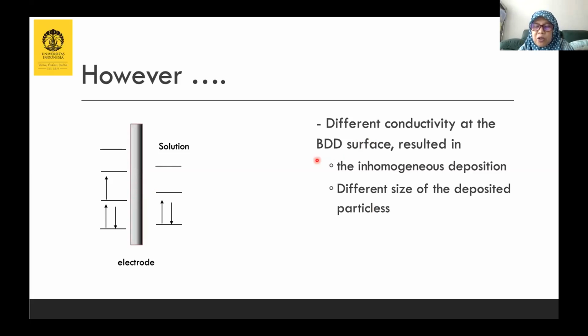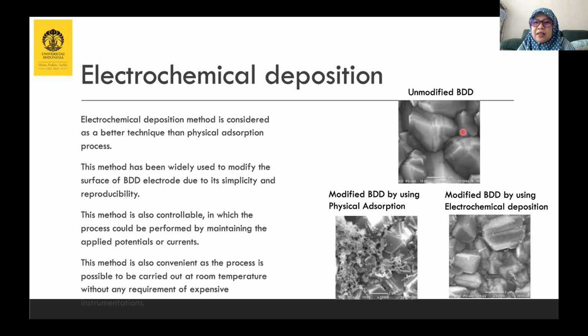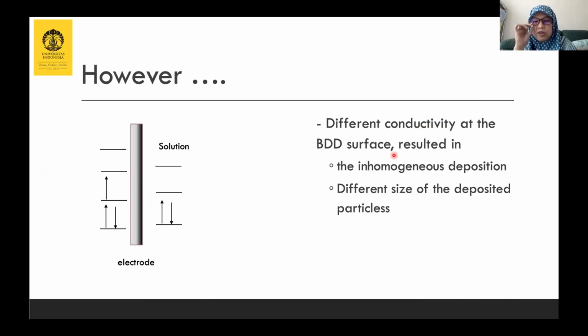But boron doped diamond actually has different conductivity, because the surface is not homogeneous, and at the border between the particles, generally there are some sp2 materials. The sp2 generally has a higher conductivity than sp3, so it can absorb more metals than the rest of the surface. So this produces inhomogeneous deposition and different sizes of the deposited particles. Of course, this is better than physical adsorption, but we still have this disadvantage.